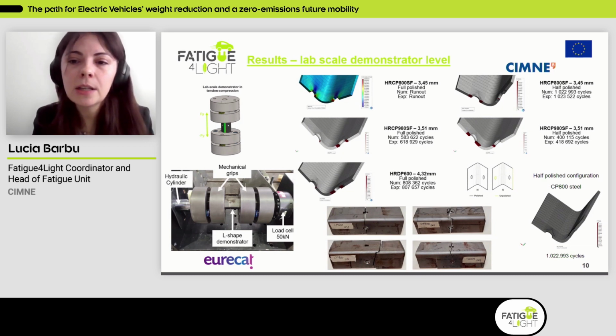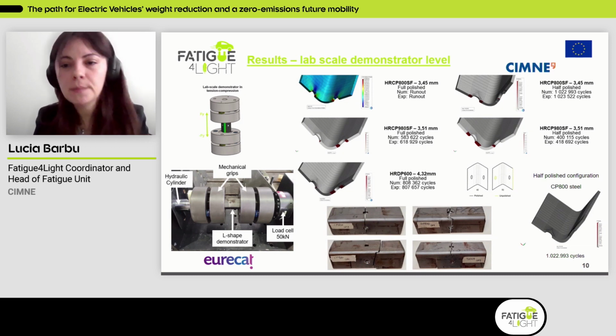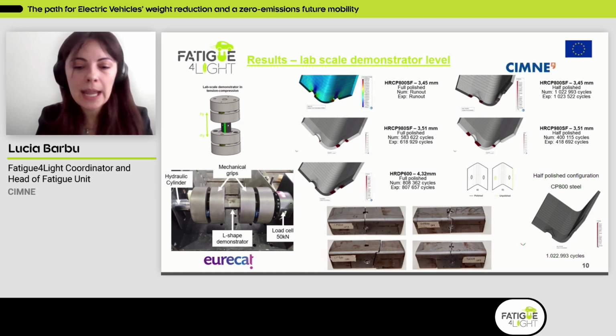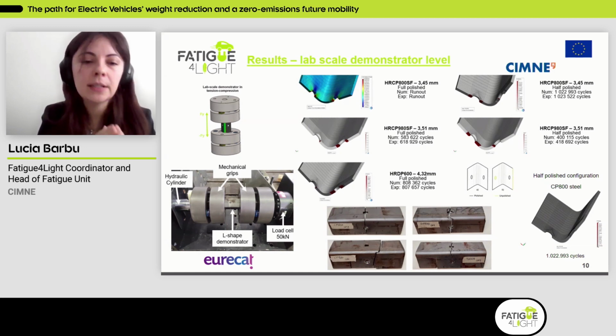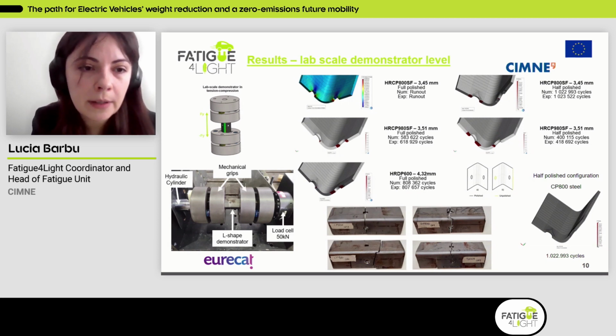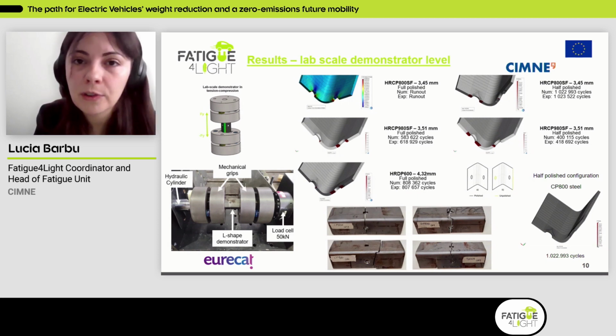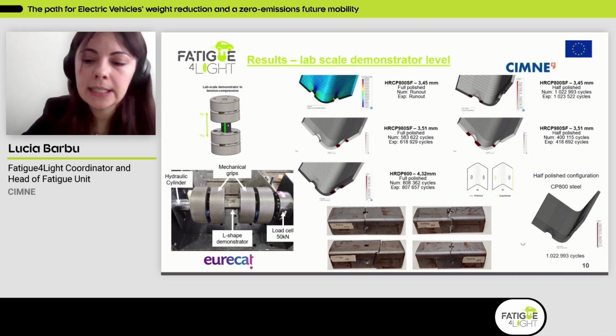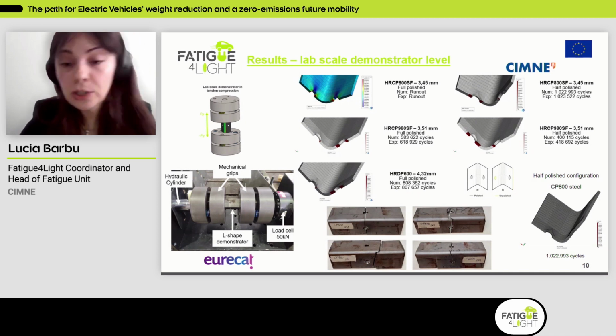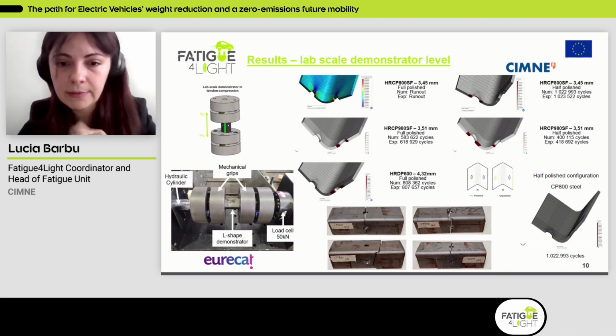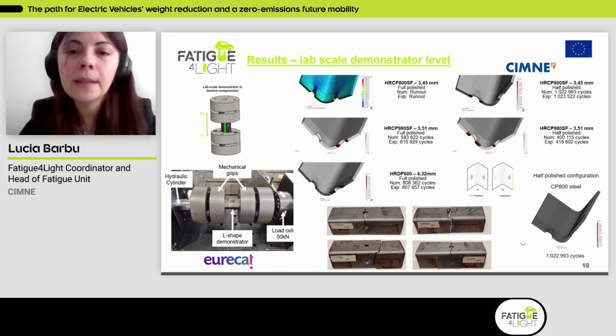And in this sense, we designed two different specimens. One was completely polished, and another one had some areas of the specimen which were left unpolished. And our colleagues at EURECAT did an intensive experimental campaign where, under a reversion factor of -1, they tested these lab scale samples. And here you can see just an image of the different failure modes that were observed experimentally,